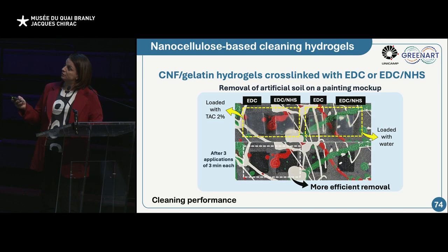Here we have it loaded with TAC 2%. And our best results are after 3 applications of 3 minutes each. So we can see that in the deepest pores of the tissues, we still have some materials to be cleaned, but overall the cleaning was very efficient.